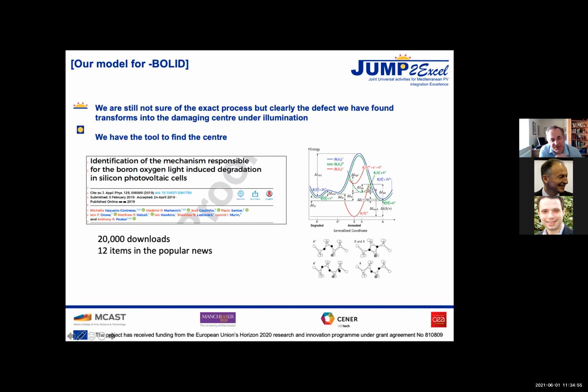So this is really interesting. We kind of solved one problem, we found another one. The next question is, why does this relatively shallow acceptor degrade the performance of the cell? And the answer at the moment, we're not sure, we don't know. But the evidence is very strong. We always see degradation. Whenever we see this precursor defect, and we expose it to light, we get degradation that anti-correlates to it.